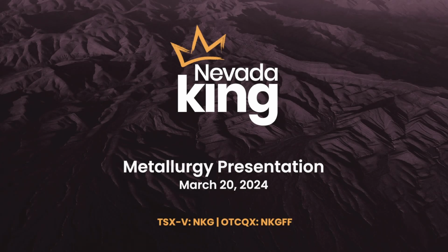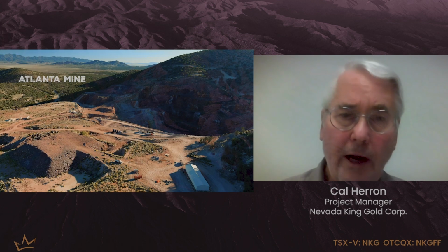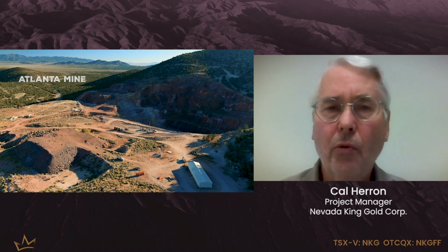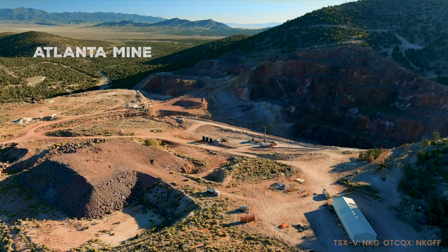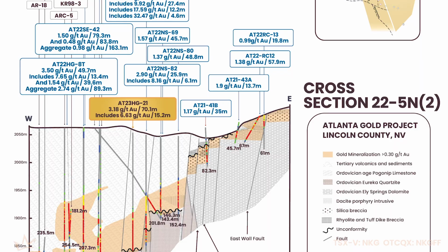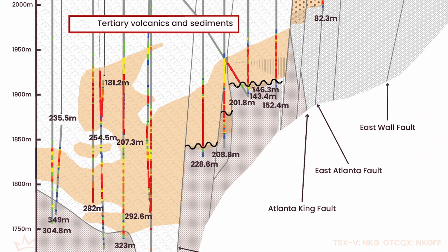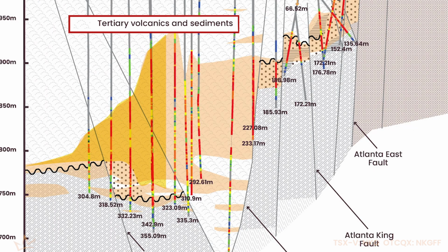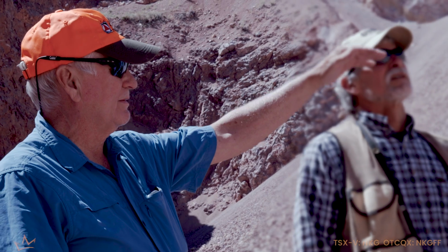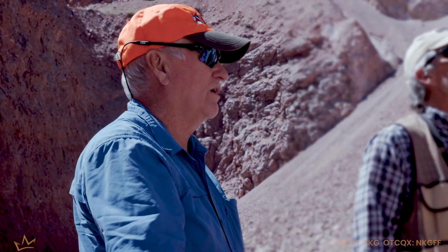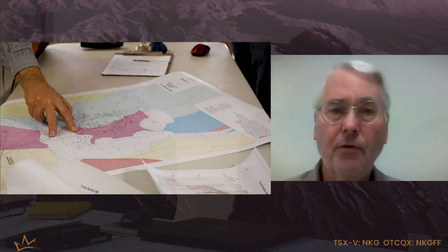The phase 2 program moved us further to the west into the West Atlanta Graben, and that's when we started seeing these thick packages of oxidized volcanics in there. And that's when we brought Gary Simmons into this program, looking at the metallurgical scenarios, both for the higher grade silica breccias as well as for the tend to be lower grade volcanic.